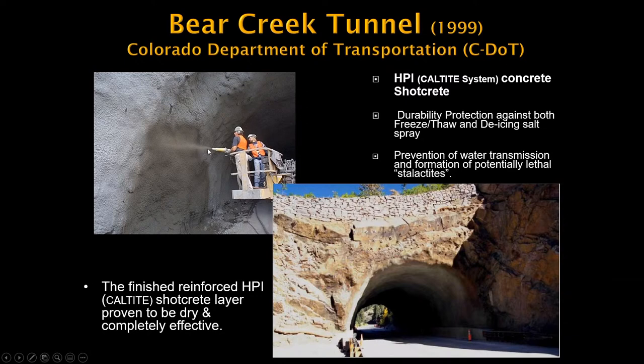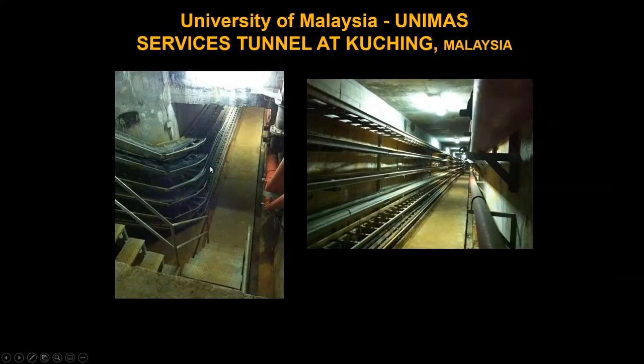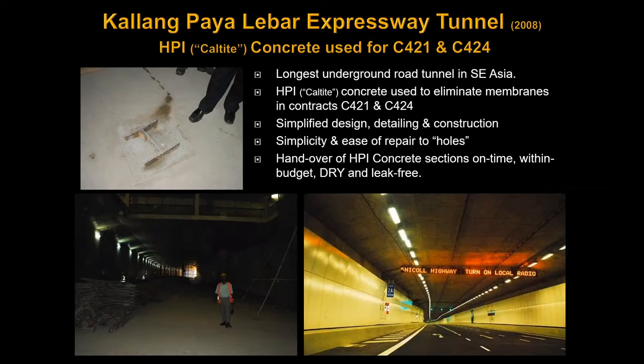With shotcrete, it's obviously very dependent on the ability of this guy here, the nozzle man, to do that job properly, make sure the concrete is properly compacted with no voids around the steel, etc. Here is an example where you've got a king post, which would normally represent a bit of a problem for trying to wrap a membrane around it. But essentially, what we do is just put an expanding joint strip around the perimeter of that HPI and cast it in. It's then cut off, and that is it. It's very, very simple. There's no messing around trying to put infills around that and then join up the membrane.